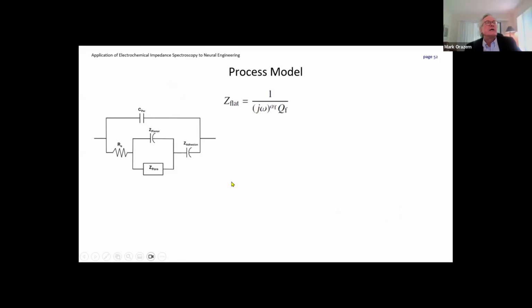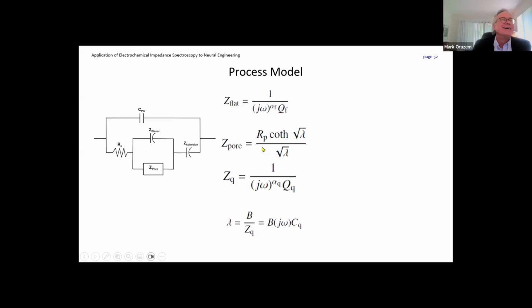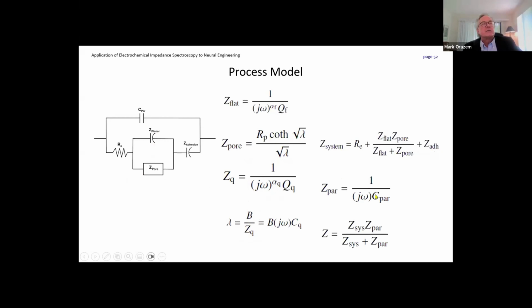So if I show this here, sorry, too many equations. But the porous electrode model is very similar to what we showed before. The lambda that we're using is a constant divided by this ZQ, which I used as ZEQ before, but this is the impedance on the pore wall, which was shown just simply as a constant phase element behavior. And so for the system, we have an ohmic resistance, we have the parallel combination of these two terms, and then we have an adhesion layer term, which looks very much like this term over here. And then the parasitic capacitance was treated as a pure capacitance.